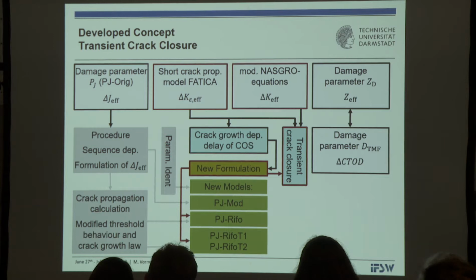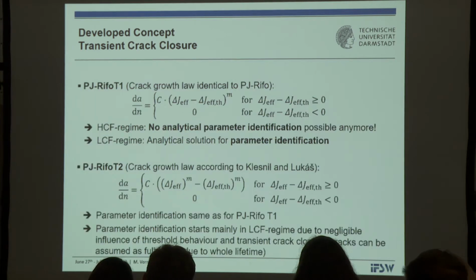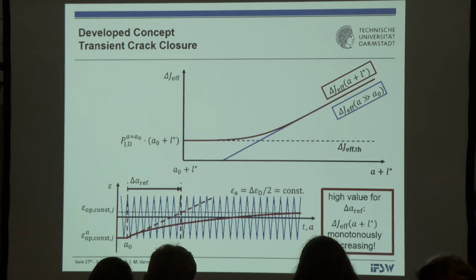So transient crack closure means that in the meanwhile, it has become clear that at the very beginning of crack growth, the crack is completely open. There is no crack wake. So this is only constant amplitude considerations. So if we really start our crack growth calculations at the crack length A0, you can distinguish here in these sketches maybe two cases. So if the build-up